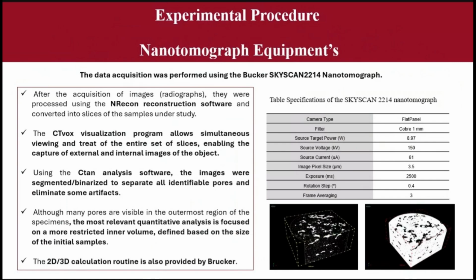The CTVox visualization program allows simultaneous viewing and tracing of the entire set of slices, and enabled capture of the external and internal image of the object. Then, using the CTAn analysis software, the images were segmented and binarized to separate all identifiable pores and eliminate some artifacts. Although many pores are visible in the outermost region of the specimens, the most relevant quantitative analysis is focused on a more restricted inner volume defined based on the size of the initial samples.